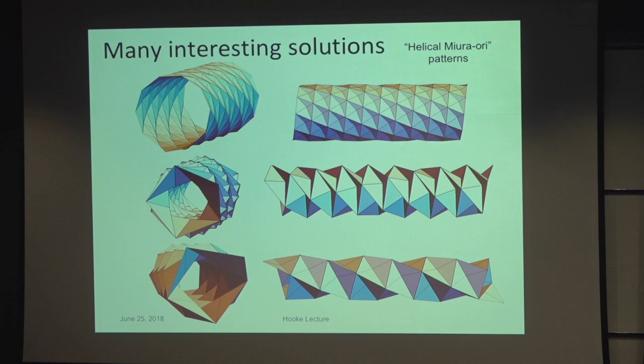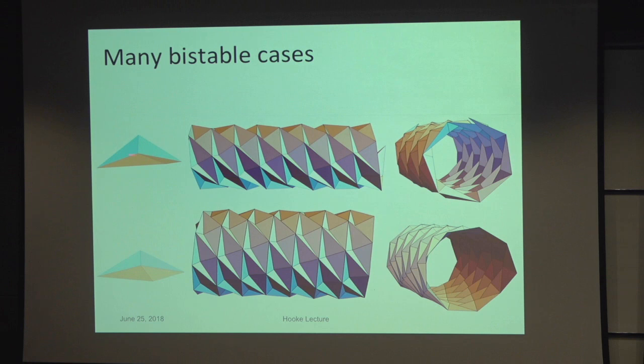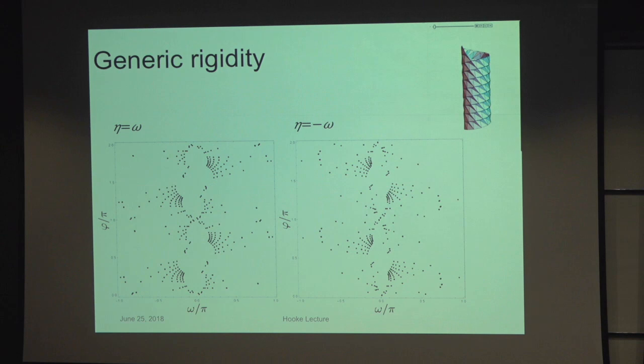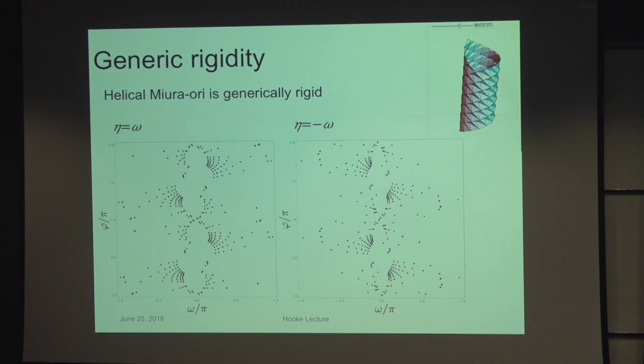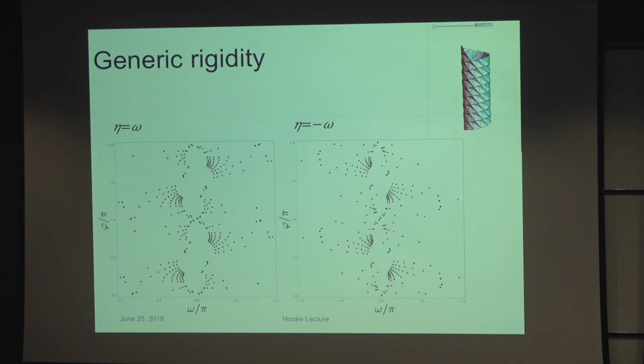Oh, this is a bistable case, like I was just describing. You have a folding, and you get this structure. You fold it a little bit more, and you can get this structure. So it's kind of bistable, and in fact, you can write the solutions. You can write solutions in terms of two parameters, and the solutions are represented by these dots. These dots are isolated, and that means, in fact, there's a little picture there. So that's jumping between different solutions. I can do it again here. And you can see you can't continuously morph this helical structure